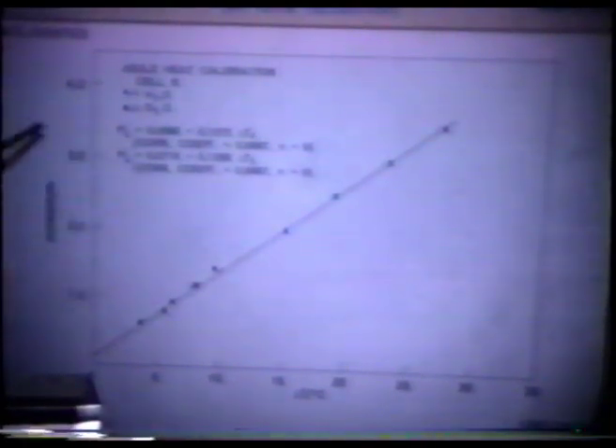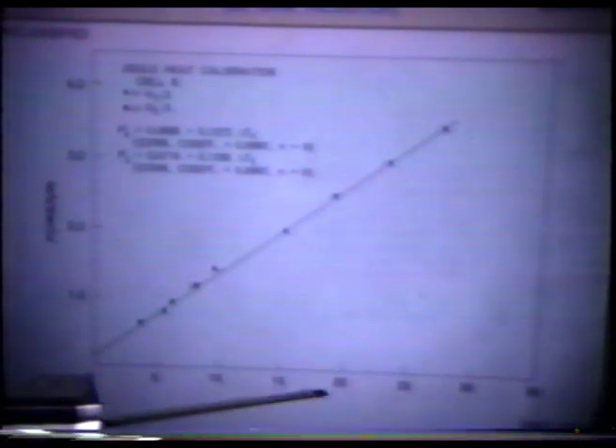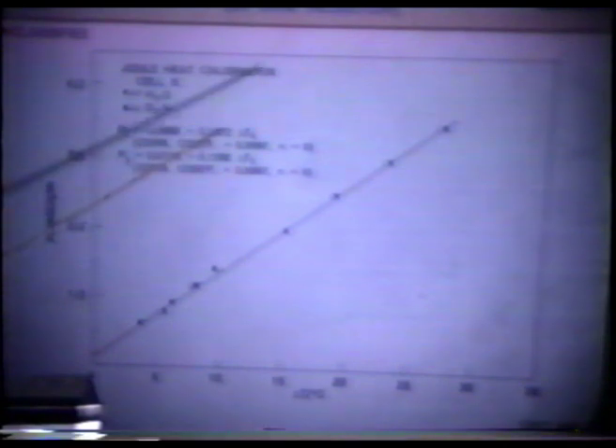But you see we get a nice linear fit of power out versus the change in temperature, the difference in temperature inside the cell and that of the water bath, that's delta T. The correlation coefficient is 0.9997, which is pretty good. Note, however, that it does not go exactly through zero. The line does not go exactly through the 0 point here, and there is a reason for that,